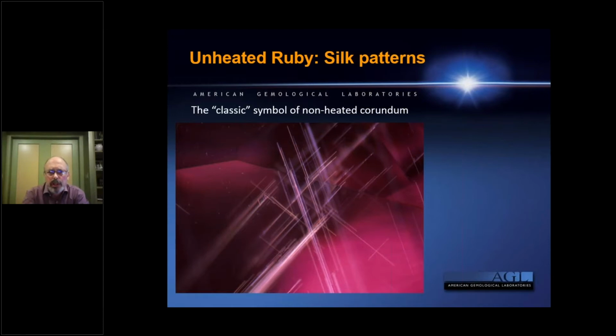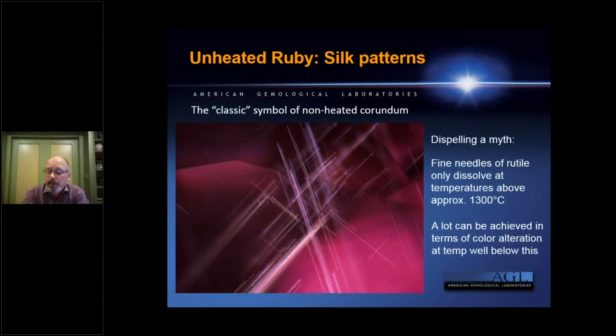We were all kind of taught that this was the sign of a stone that's unheated. But I really want to dispel a myth, because this is a fallacy. We know much better now that fine needles of rutile only begin dissolving at temperatures of about 1300 degrees centigrade. This isn't a fixed point. There are a lot of factors which will influence when rutile actually begins the process of dissolution in stones, but it's plus minus around 1300 degrees.